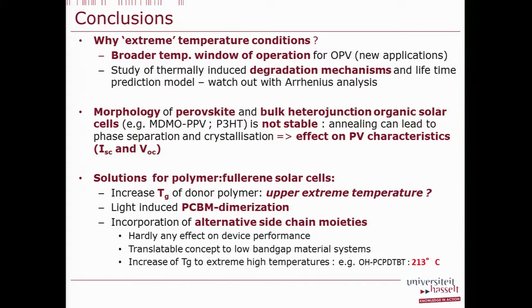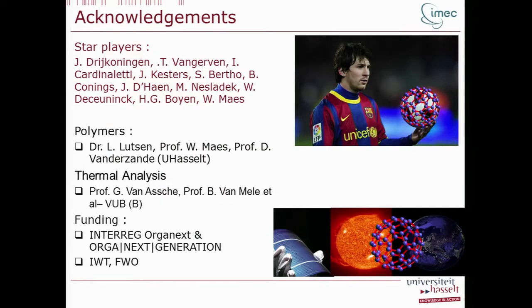We've seen this light-induced PCBM dimerization, and that the incorporation of alternative side chains can improve also the thermal stability of the morphology. And in terms of extreme temperatures, it has been demonstrated that also a TG of 213 degrees Celsius has been reached.